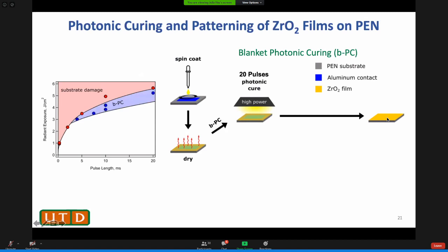In this case, the region that got converted is determined by the shape of the bottom metal. So it's only converted on top of the aluminum. If you lower the energy some more, then nothing will get converted. So you zap it and you develop it, everything comes off.